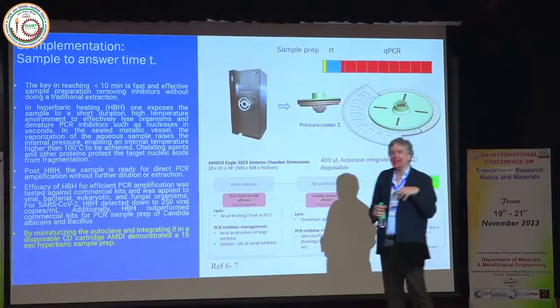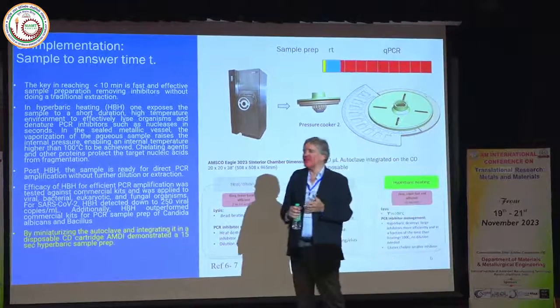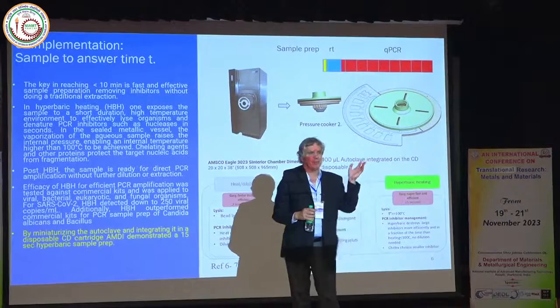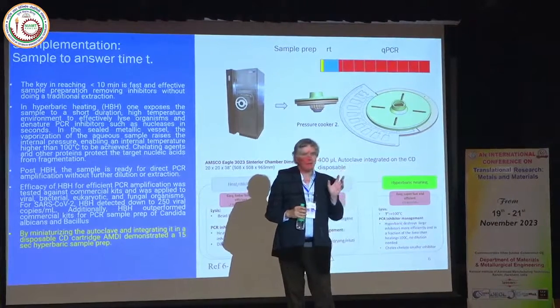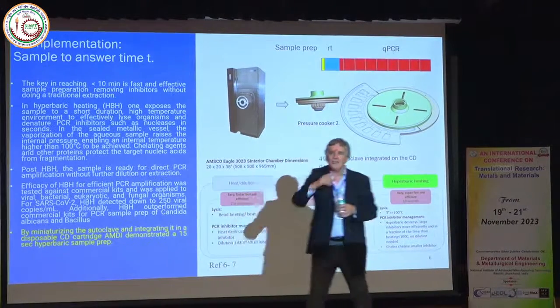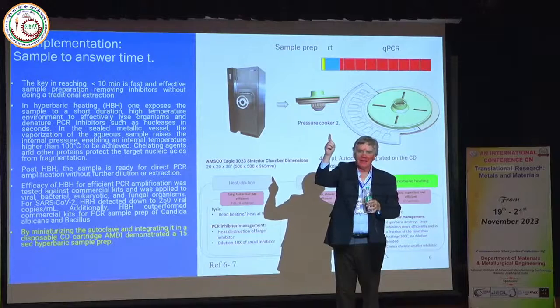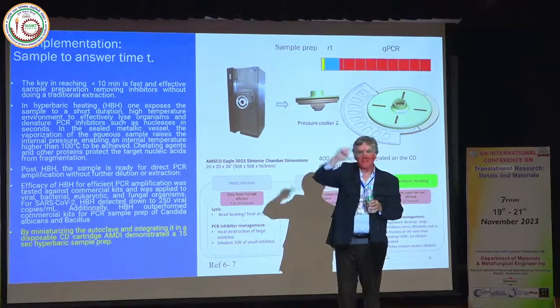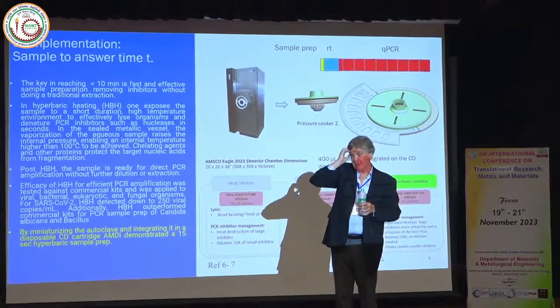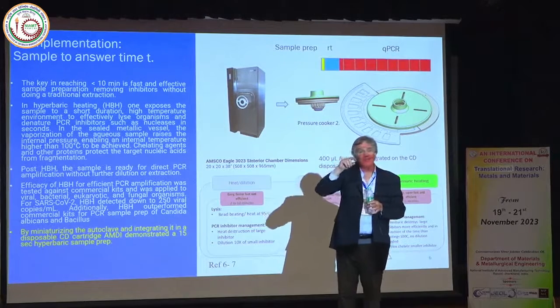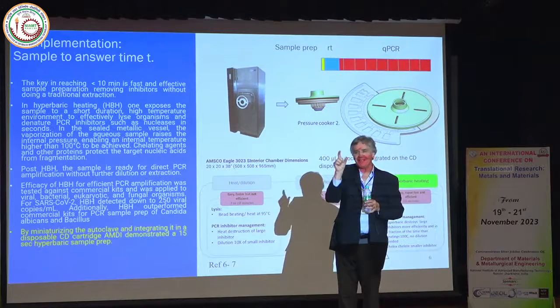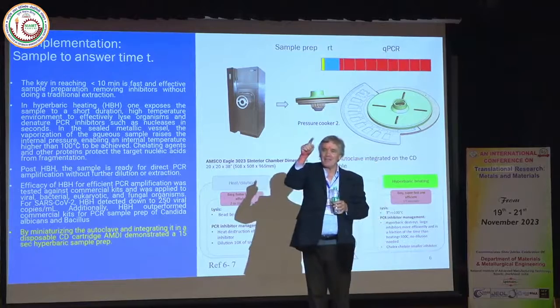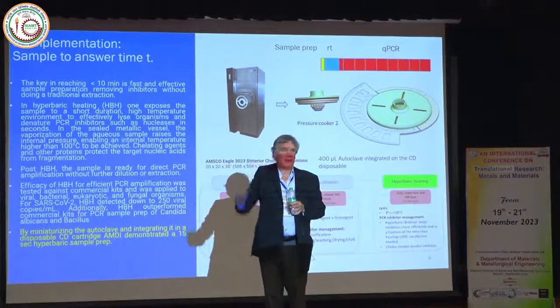Now people say, I can do that. Your RNA is not very stable, it will all disappear. Now what we found is that if you only do it for 15 seconds, you can actually do the best possible sample preparation. So if you do it 5 seconds, not enough. 10 seconds, not enough. 15 seconds. Because then when you go longer, it starts decaying.